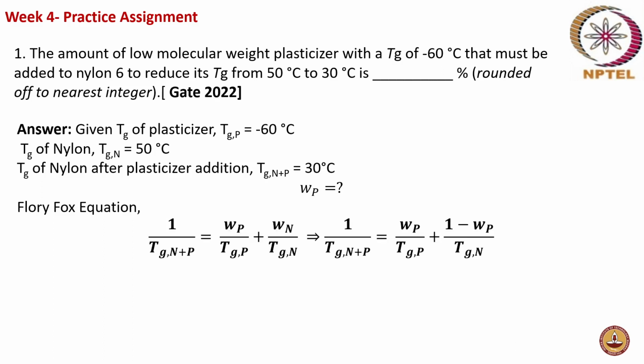So you have the Flory-Fox equation, which gives 1 by Tg of the system with nylon and plasticizer, the overall system, equal to weight fraction of plasticizer by glass transition of plasticizer plus weight fraction of the nylon polymer divided by glass transition of nylon polymer. This is again a small molecule, low molecular weight plasticizer that is being added. So you have only two components, your plasticizer and nylon. So your weight fraction of nylon can be expressed as 1 minus weight fraction of plasticizer, correct?